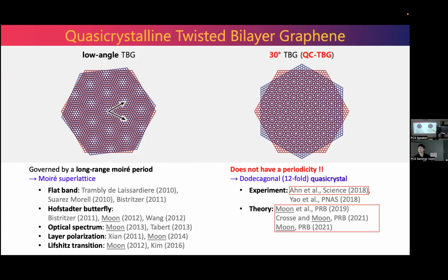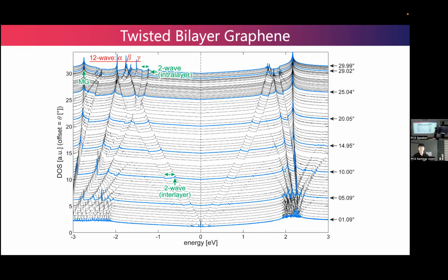However, twisted bilayer graphene at exactly 30 degrees is special because it does not have global periodicity. Although we can see similar patterns, they do not appear in a periodic way. In fact, this is a quasicrystal structure, which does not have a periodicity. And we had a glance of such features.